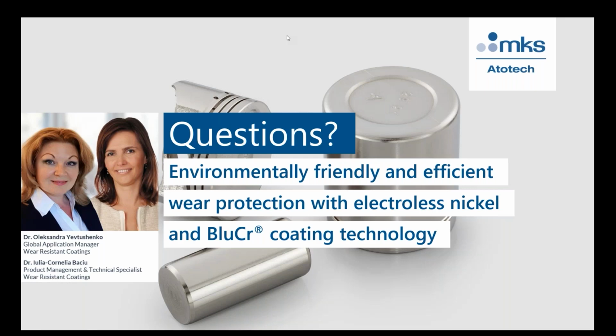Basically, if we are talking about mist suppressants, during the hydrogen evolution, which is the concurrent cathodic reaction during plating, some electrolyte droplets will be taken out with hydrogen, and we will see so-called spray misting. And this leads, of course, to air pollution with aerosols containing these electrolyte chemicals. Because of that, exhausts and mist suppressants are usually used.